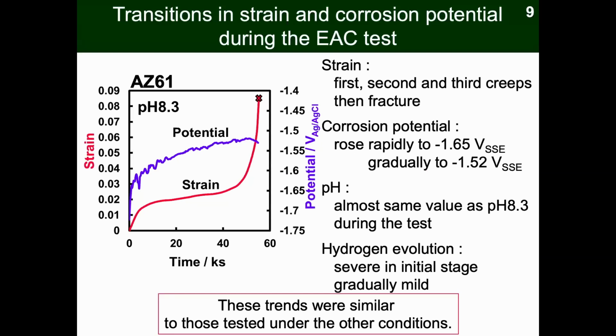Here is a result of the EAC test of the AZ61 in the carbonate solution of pH 8.3. And here is a typical transient of the strain and potential depending on the test time. As you know well, the strain transition was first, second, and third creep stage. And corrosion potential initially goes up to this value and gradually goes up to minus 1.5 volt.